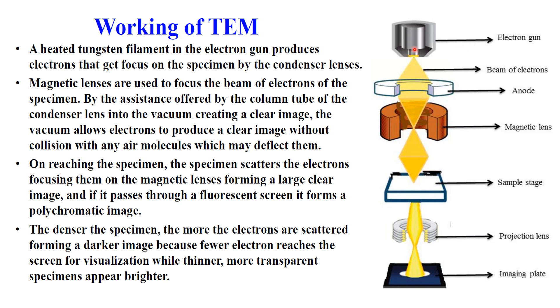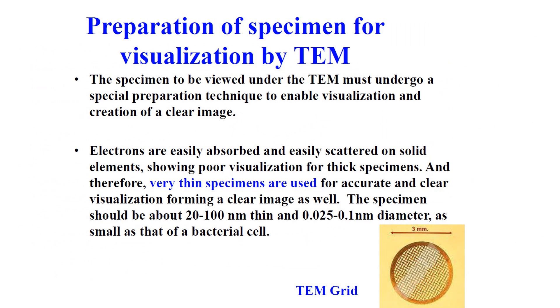Again, the electron gun creates the electron beam and magnetic lenses are used to focus it. The whole setup must be in vacuum. The sample must be thin so that sufficient electrons pass through to give bright images; a thick sample allows very few electrons to pass through. Sample preparation is very important in TEM. Special TEM grids — mesh-like structures about 3 millimeters in diameter — are used, and the nano-powder or film is placed on the grid, then put on the sample stage for imaging.